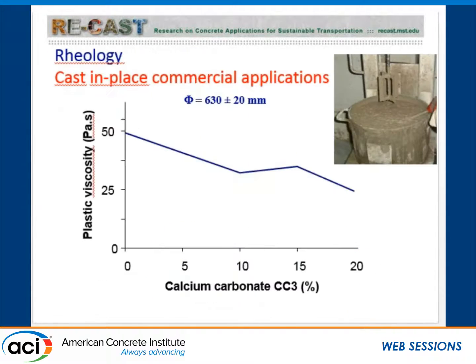We also looked at the rheological properties. So this is an example of SCC for commercial application. The slump flow is maintained, so the yield stress is the same. And then we see that the plastic viscosity with the replacement goes considerably lower, 40-50% lower. And for cast-in-place application, that has a lot of benefits for surface quality, for ease of pumping, ease of finishing, placement. So viscosity is important, but of course you have to make sure that it's not too low because that will get you in trouble in terms of stability.